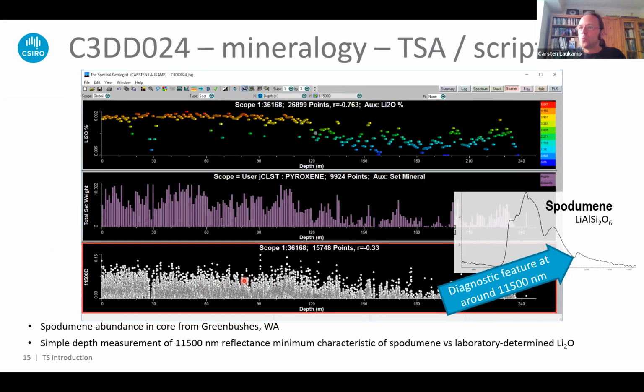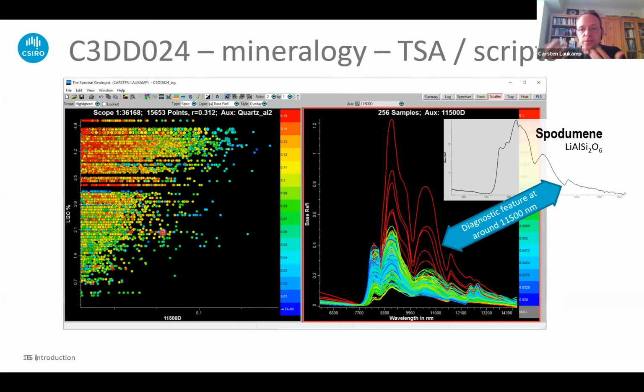You can also generate different scatter plots in TSG, the Spectral Geologist software. You can plot the lithium content here on the y-axis versus this feature at 11,500 nanometers. That's typical for spodumene, and you can see this kind of diagram.